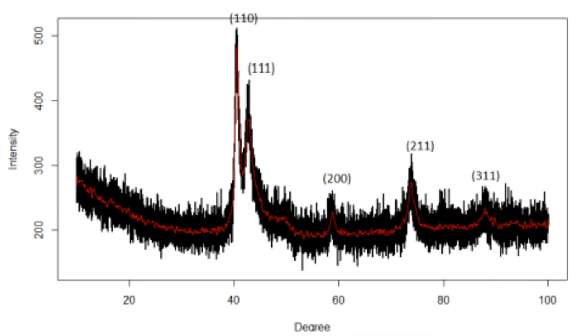As copper and molybdenum were so identifiable, this suggests that they do not react with the other powders to form a high entropy alloy during milling. A high entropy alloy therefore did not form with 20 hours of milling, and a longer milling time would be required. A 30-hour sample has been milled for this combination, but is yet to be analysed through XRD analysis.